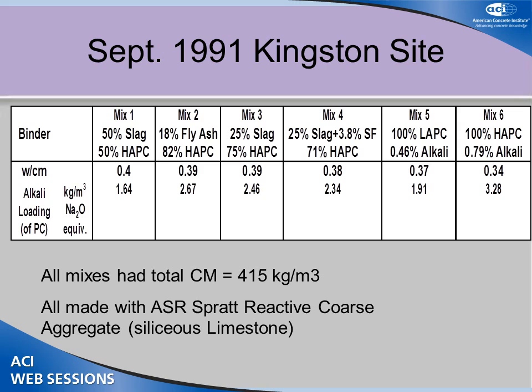We also tried 25% slag because the highway department generally allows 25% slag in all their concrete, but you need special permission to go above that. So we wanted to see what that would do, even though we knew it wouldn't control the ASR on this one. We then used a ternary mix because in their high-performance bridge specs, and a number of other high-performance projects in Ontario, they typically use a blended silica fume cement with 25% slag in that as well. Now, the blended silica fume cements they normally use are 8%, but we didn't have enough bags of silica fume blended cement on site. We miscalculated, so we ended up using 3.8% silica fume in the total blend.